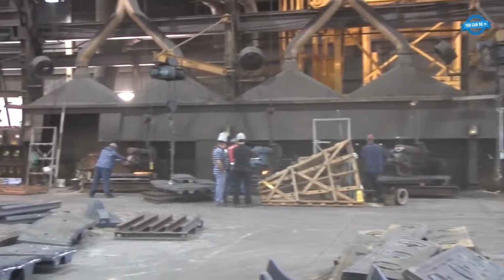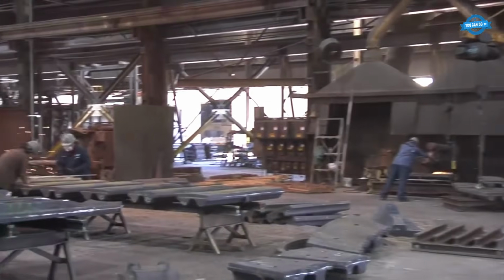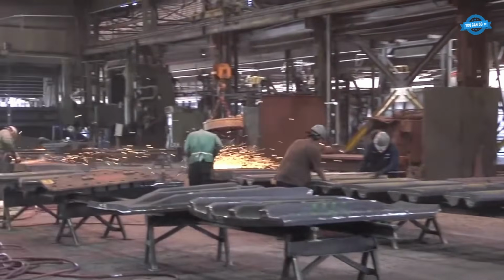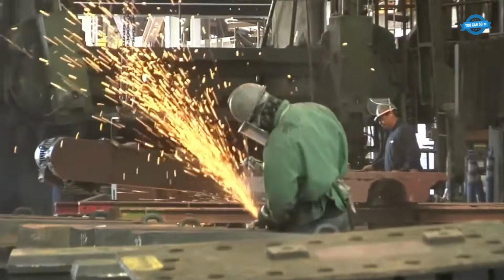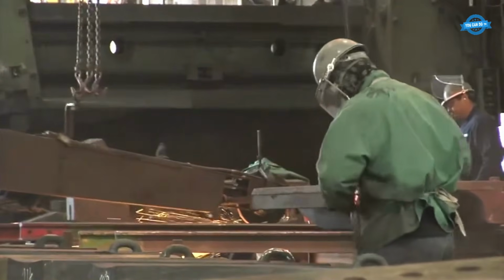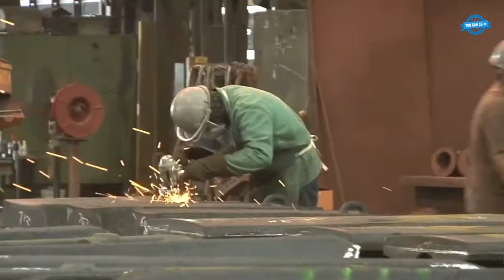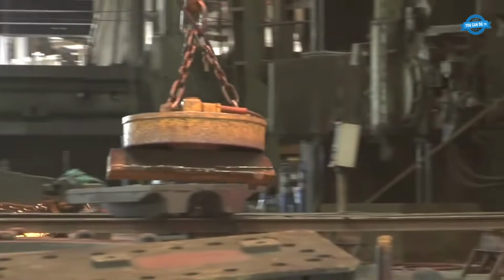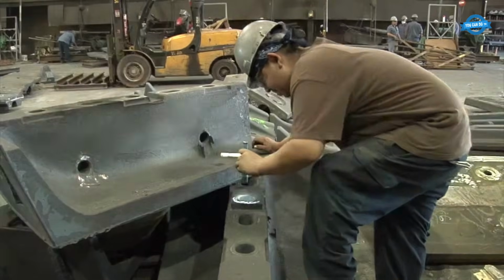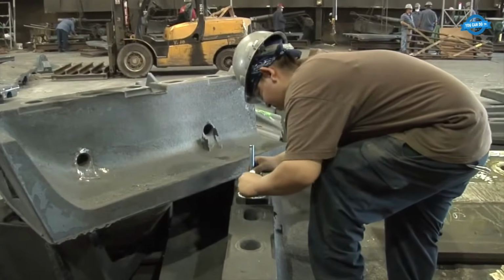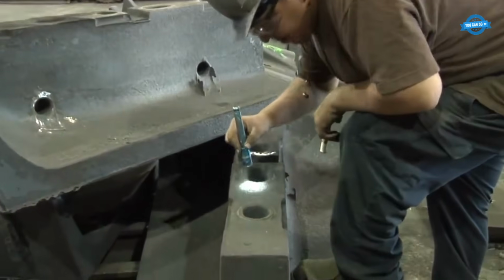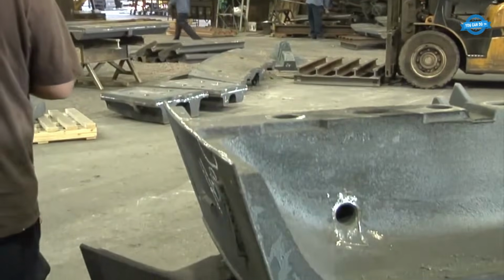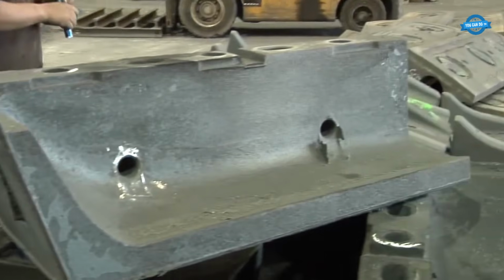Pins verify locations, while computerized Brinell testing records hardness against each serial number. For mill liners, hardness predicts wear life, which customers convert into operating hours before shutdown. Inspectors confirm measurements, then mark approved castings with a green dot. No dot, no shipment. A casting can look right outside and still be wrong inside until every check confirms it for service.